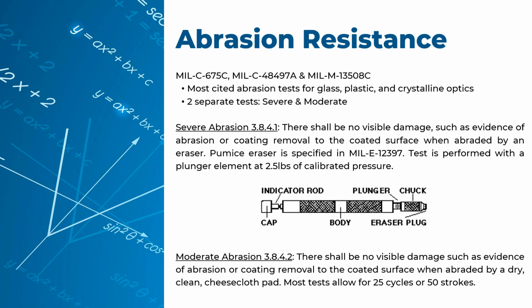For some severe abrasion and even some moderate abrasion testing, if the matrix of tests requires it, you'll do a severe abrasion and then do an adhesion test. You can do a humidity test, then severe abrasion, and then an adhesion test. So it really depends on how you want to stack the testing matrix and how you want to specify the tests are conducted. So those are a couple of abrasion requirements that exist, severe and moderate abrasion for those mil specs.